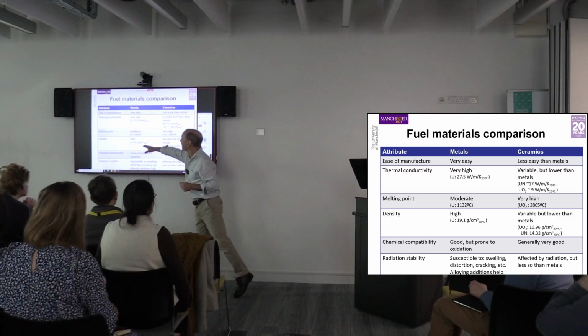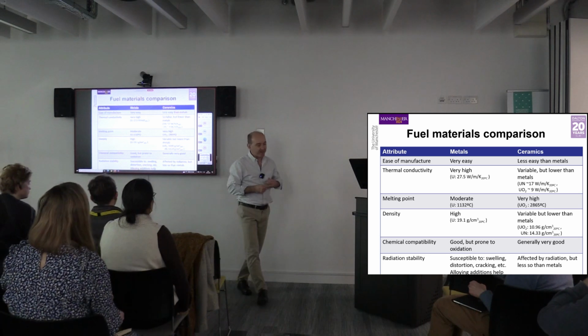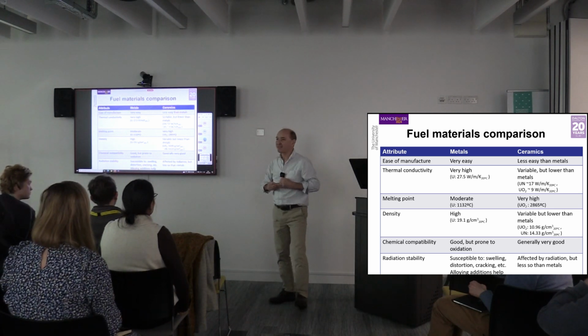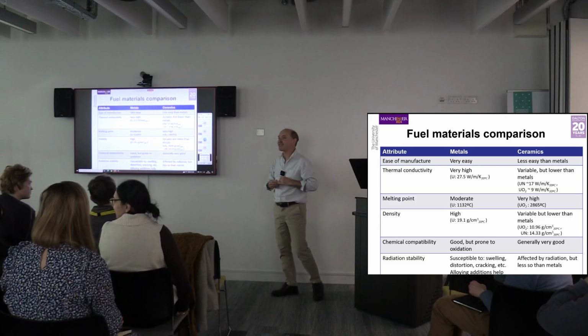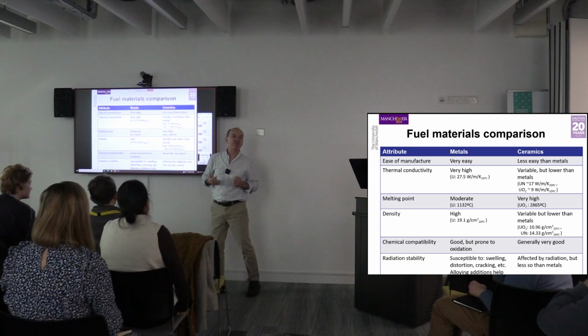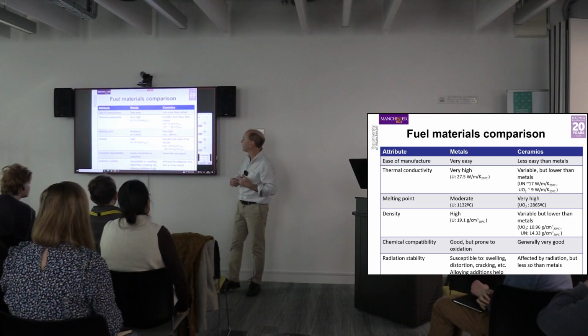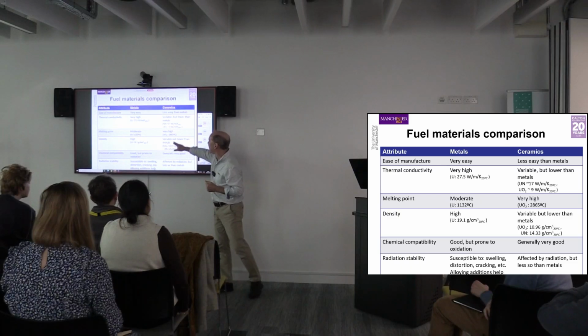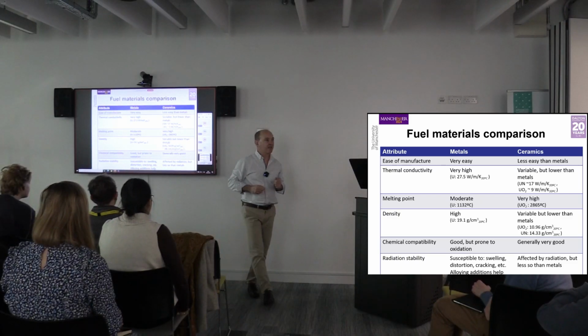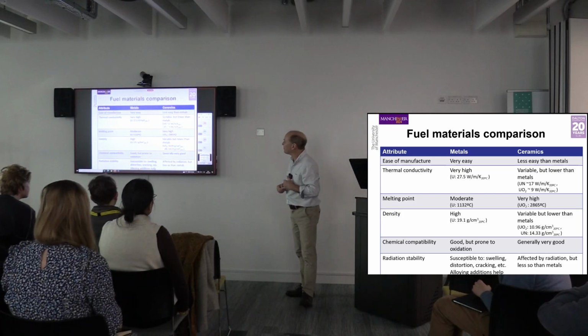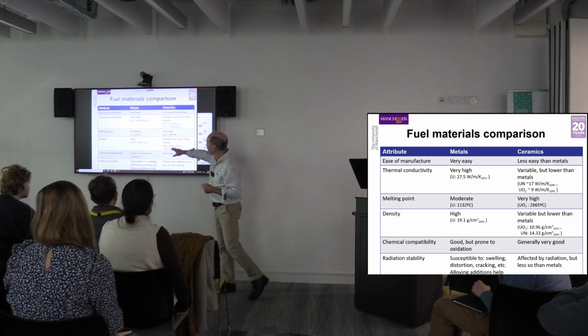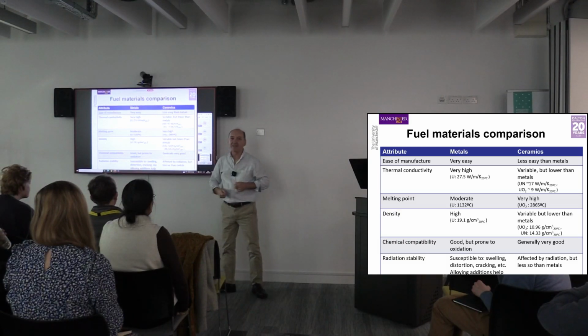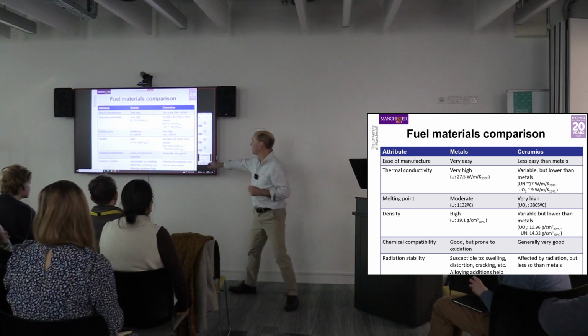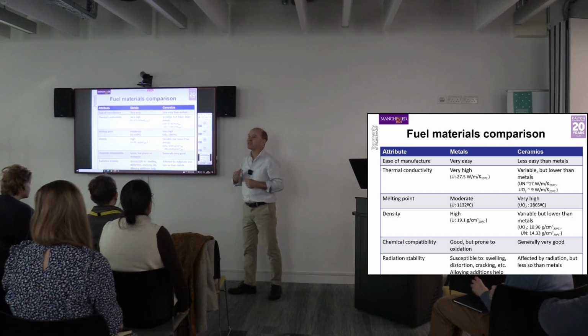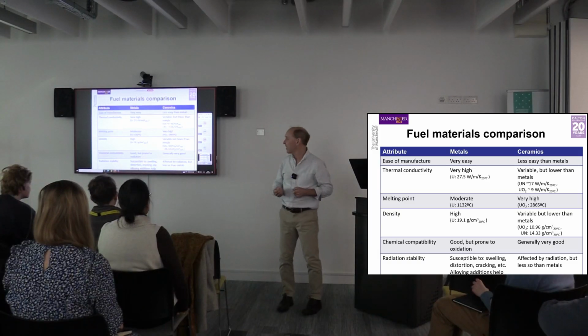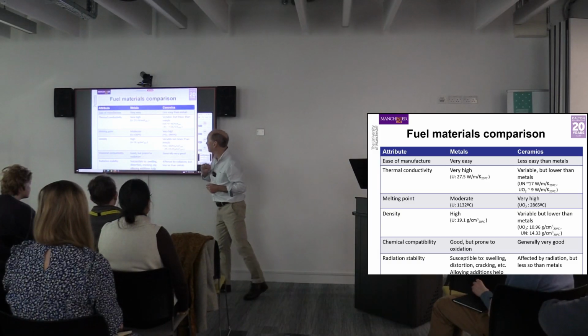Metals, very dense, extremely dense. If my head was made out of uranium, and there are those of you who know me might think that perhaps a similar kind of density might be obtained, then yeah, my head would weigh about a ton if it was made out of uranium. It's very, very dense indeed. Ceramics, lower. Again, quite variable, but much, much lower density than metals. Typically half if we're thinking about UO2. So UO2 is still pretty dense. If you compare it with a cubic centimetre of water, the density of about 1 gram per cc, then this is 10 times or almost 11 times higher, but still nothing like the same density as uranium metal. So big win for uranium metal when it comes to density.